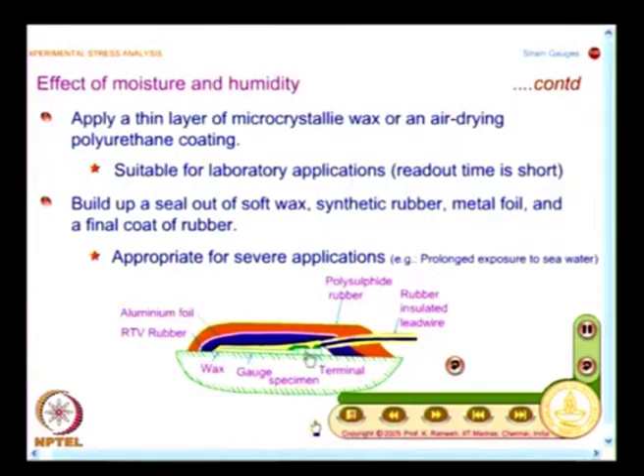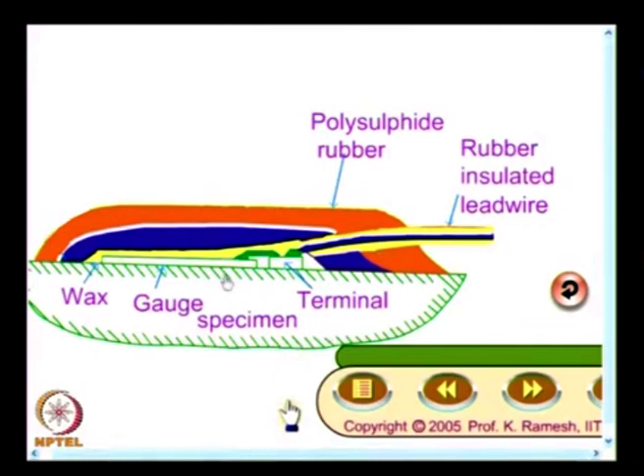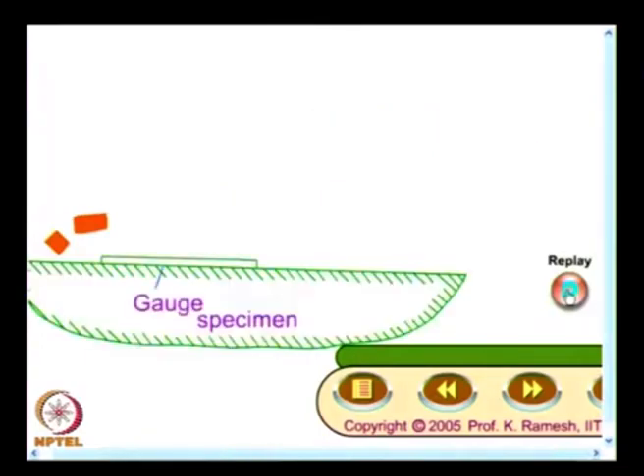And I would like you to have a neat sketch of this, a figurative sketch. So, what you essentially have is, on the specimen you have the gauge, then you have a coat of wax, then you have a coat of rubber, then you have aluminum foil, and have a final coat of polysulfide rubber. And this also you can see as animation where you see one layer after the other.